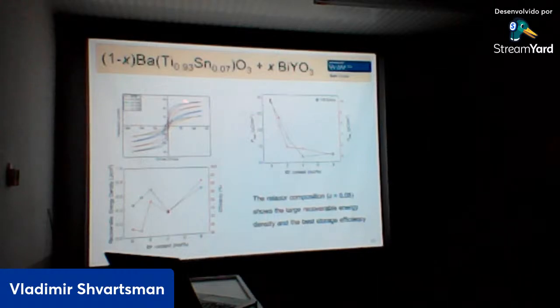And when we now calculate our energy storage parameters from the bipolar hysteresis loops, you see here the black points correspond to the recoverable energy density, and the red points correspond to the efficiency eta. You see that these materials, like this one with 8% of the bismuth yttrium oxide, are very good. It has large energy density and also large efficiency. Of course, this energy density is still less than I showed in these films, but these are bulk ceramics, so the electric field is still pretty low. It's only 150 kilovolts per centimeter in comparison to 4,000, which were shown before.